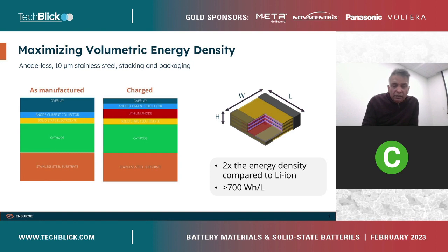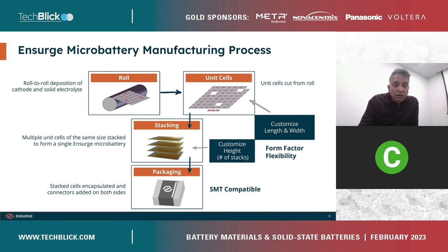Another part of being able to get the high energy densities is to have end termination, so we don't waste space on contacts. A quick overview of the manufacturing process. We start with rolls. We have just one single patterning step. This allows us to use inventory across the board, and it's very important for manufacturing inventory optimization. This gets into test, where we test the good cells, stack the good cells, and then into encapsulation, metallization, packaging, and test.